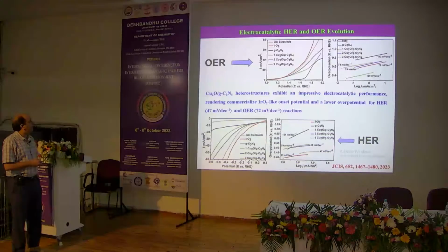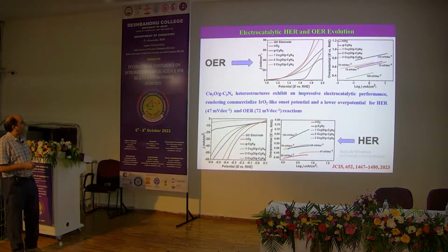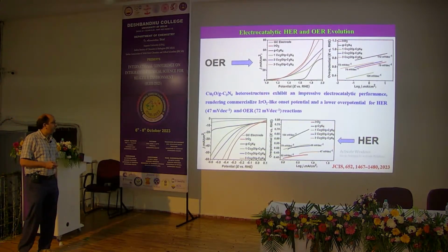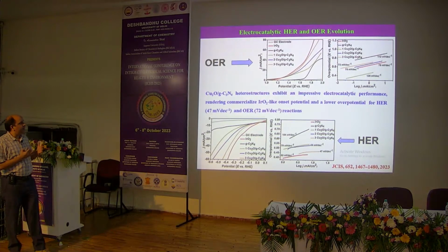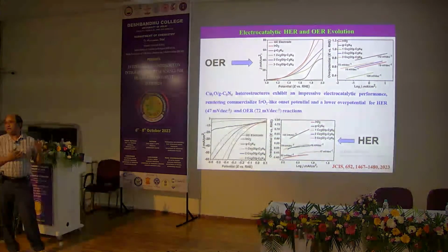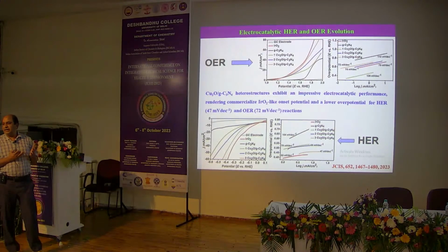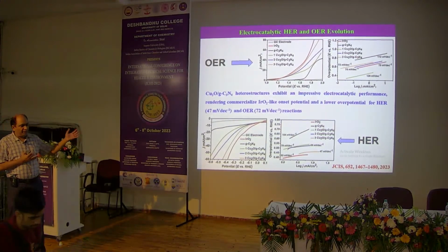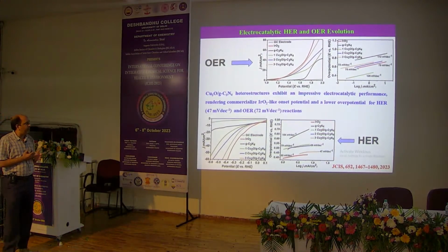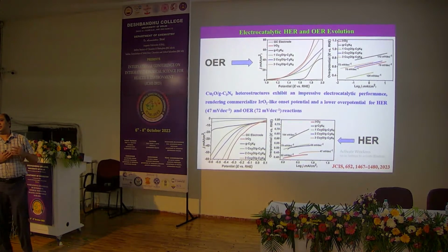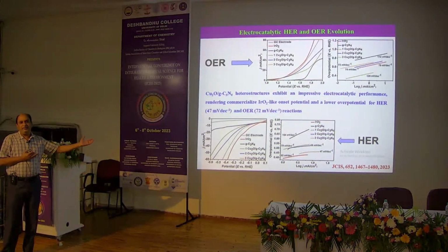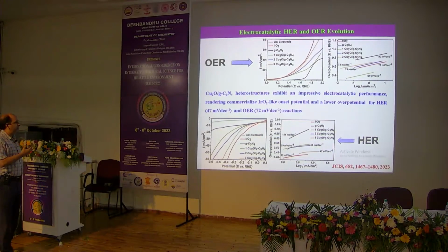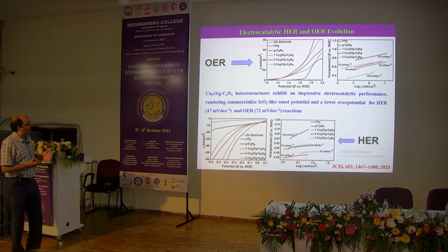Then these are the HER and the OER reactions. Both these investigations show that this gives very impressive electrocatalytic results, and we have shown, on the basis of our results, that these as-prepared binary heterostructures could be the best replacement for the commercially available iridium oxide. Our results were quite comparable to iridium oxide.